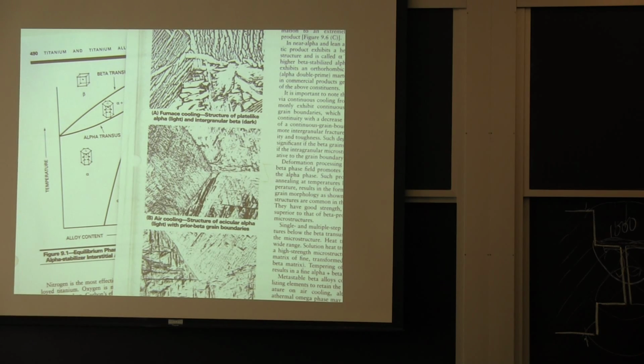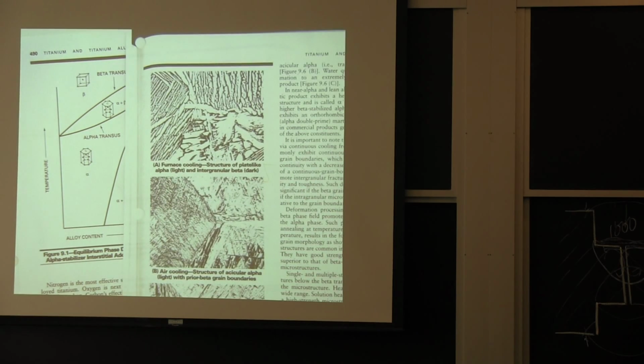structure. I had a student in the early 80s working on helicopter rotors over here at Watertown Arsenal. The Army wanted to use castings. You cast titanium or anything else, you're going to have defects in the casting. Can't throw out a $50,000 casting. You got to weld repair it. And the question was, are the weld repairs going to be any good? Gordon proved the welds were better than the base material, because you got a better cooling rate. They gave us a finer structure.